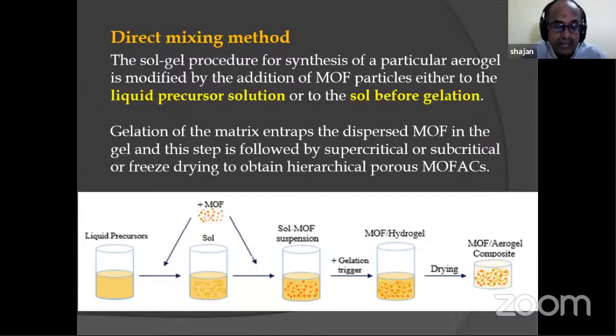So all these three things you have to be careful about when we are doing direct mixing. These are the important precautions. Before starting, you have to check whether your MOF is water soluble, whether you are using water in your precursors or water as a solvent in your aerogel synthesis. All these things you have to check, and you should be very confident that the MOF is not being disturbed while adding it.